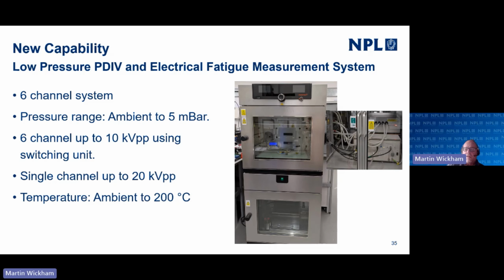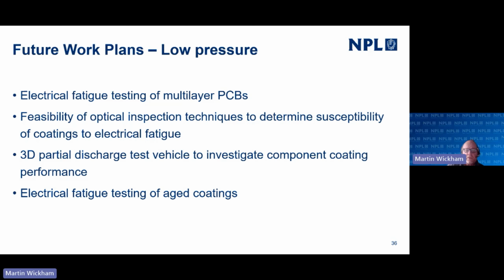We can go lower. We are limited in the upper voltage at the lower pressures because we start to form corona discharges in air at low pressure. So we have to watch that. But the system is, as I said, device agnostic, so we can plug anything on the end of these systems.